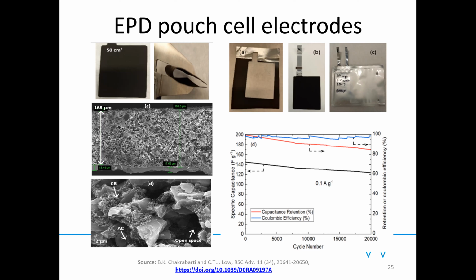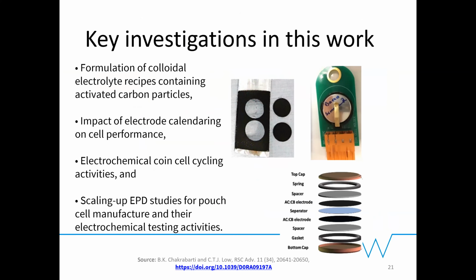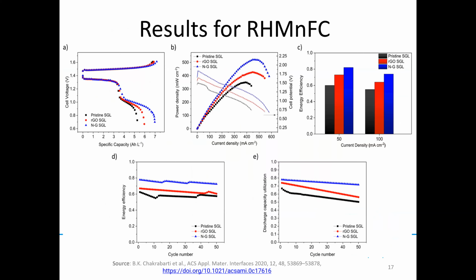Any other questions? If not, I also have one more. For the flow battery results, you have an apparent increase in the performance of the coated surfaces. When you compare the GO coated and the doped graphite coated, is it the quality of the coating or the inherent properties of these two materials playing a role in those performances, like the conductivity or hydrophilicity of the materials you are using, or are they giving a different quality coating on the carbon paper?